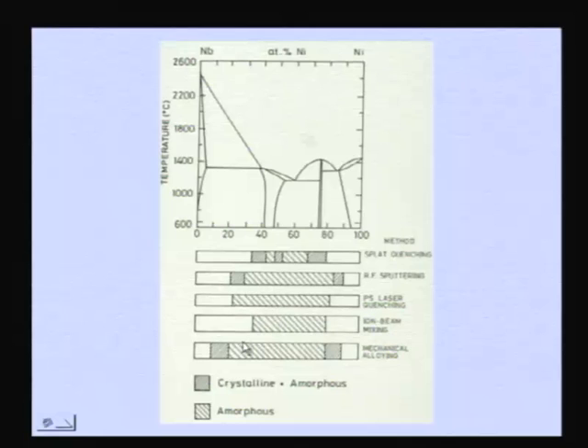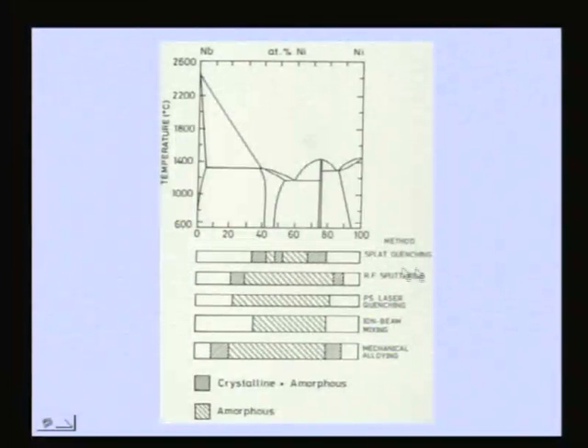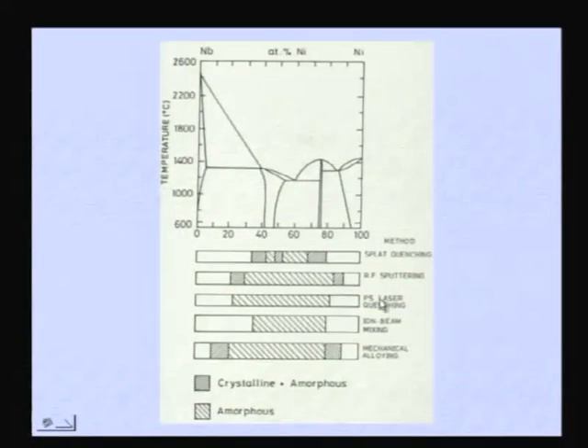And this is another interesting thing. For one particular system, this is a nickel niobium system, we are showing you what glass forming ranges you can get by different techniques. You can see all these hatched ones, the big hatched ones is all amorphous composition range. So you can see that range is very small for splat quenching. Splat quenching means gun quenching, okay. And then if you do RF sputtering or laser quenching or ion beam mixing and mechanical alloying. Mechanical alloying shows you a very wide composition range. So the glass forming range can be very wide.